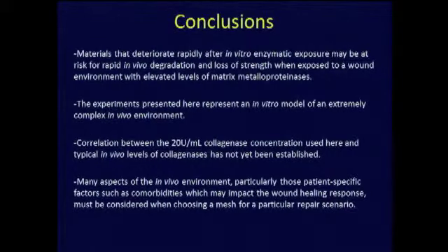Also in conclusions, the materials that deteriorate rapidly in vitro enzymatic exposure may be at risk for in vivo degradation depending on the wound environment. There are some caveats to this. The experiments presented are an in vitro model, and the in vivo environment is very complex. The collagenase that we used is a standardized collagenase, and may not be representative of a tissue environment. Thank you very much.